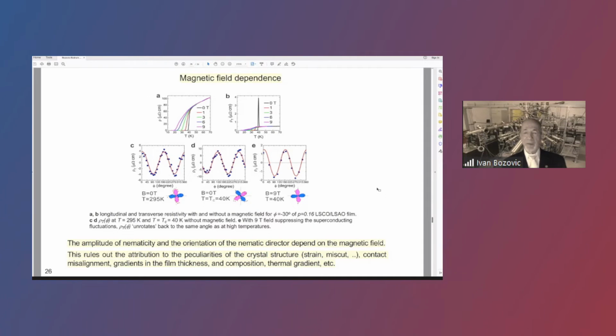But you can also see that the orientation of the director changes with temperature. In zero field, when you go from room temperature to Tc, it rotates by about 45 degrees. But when you put in a magnetic field of 9 Tesla, it then rotates back to the high temperature zero field orientation. And obviously this cannot come from the crystal structure because it doesn't change as a function of temperature, nor from any other random extrinsic factors.